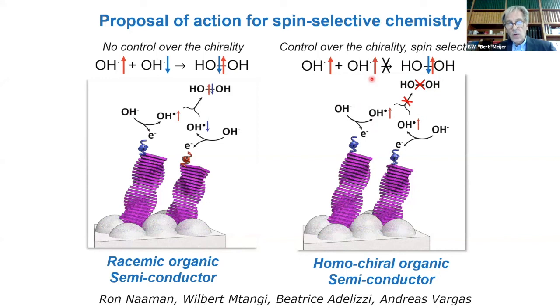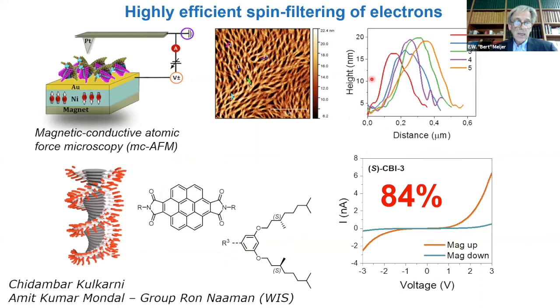But on the other hand, we want to increase the selectivity of the spins. That's done by Chidambar Kulkarni, together with Ron Naaman's group. He synthesized this molecule. It has chirality in it. It has stereocenters. And if you do it right, it goes into one helical form. Then you spin coat a film, and you take an AFM, and you see bundles of these structures with different heights that you see over here.